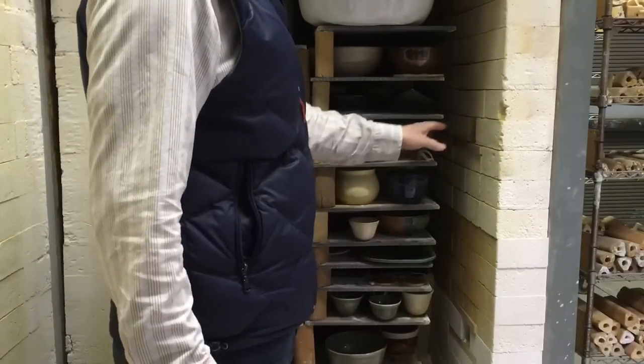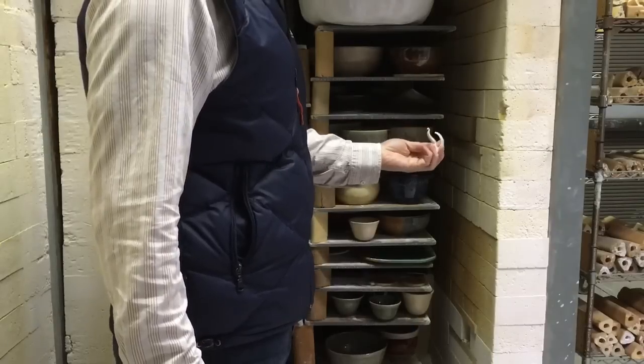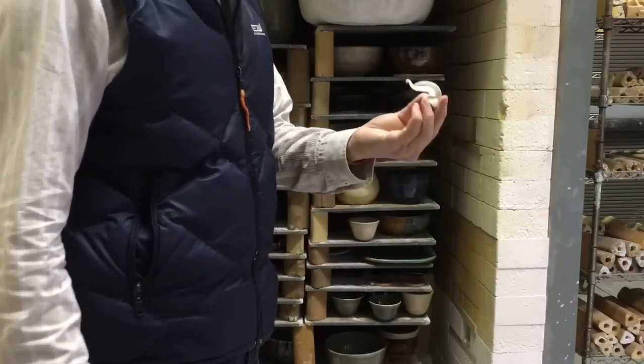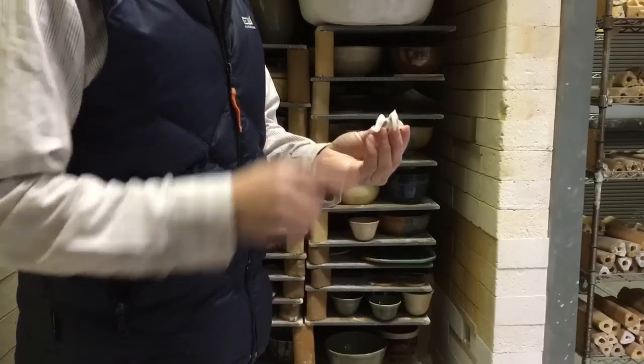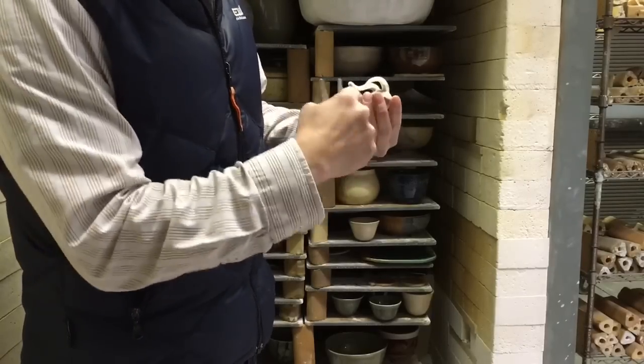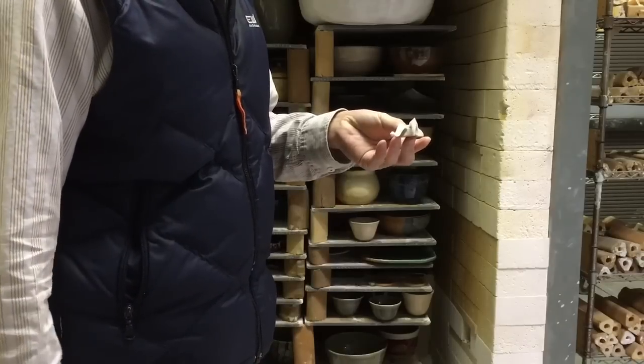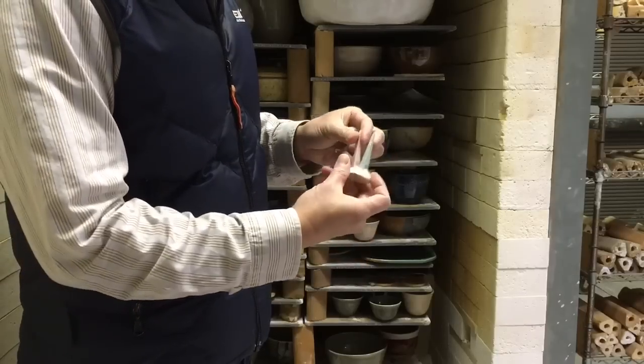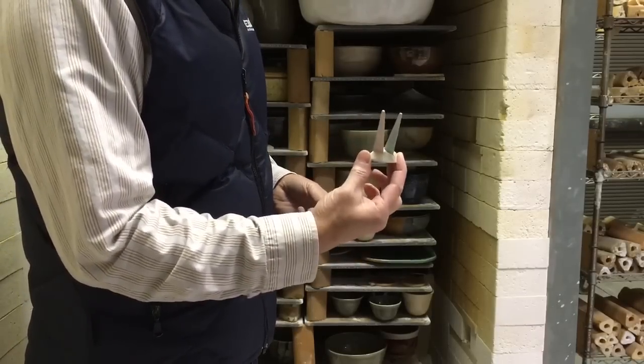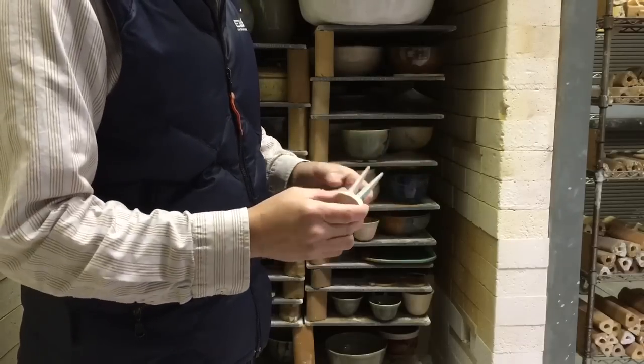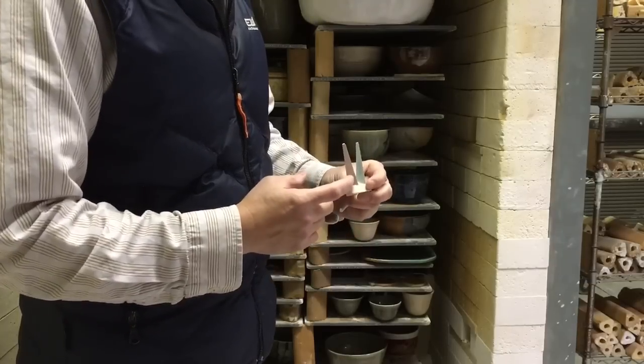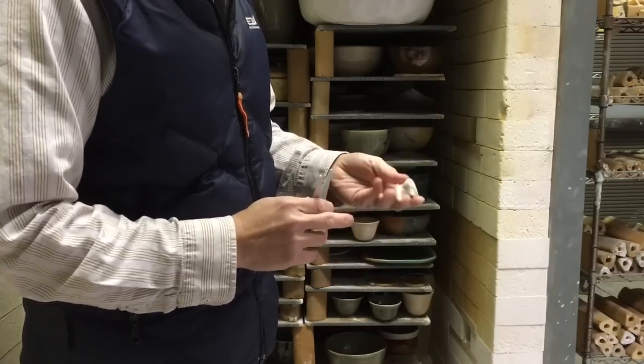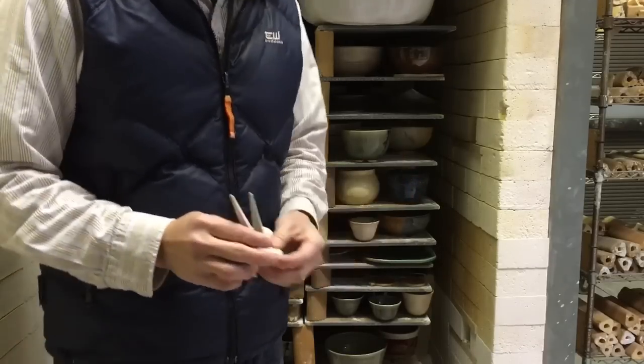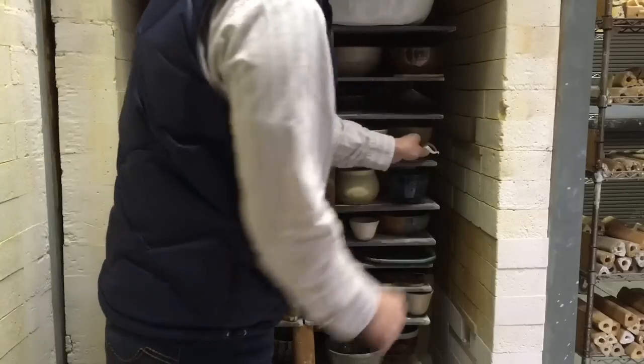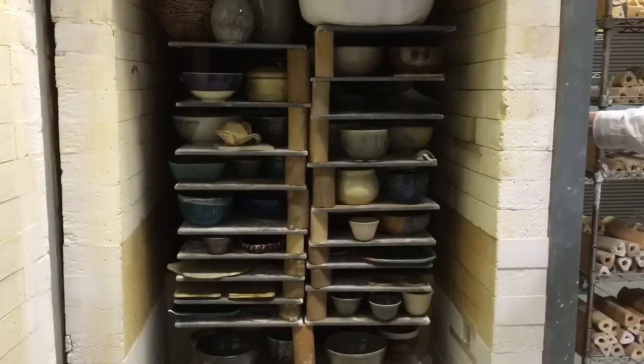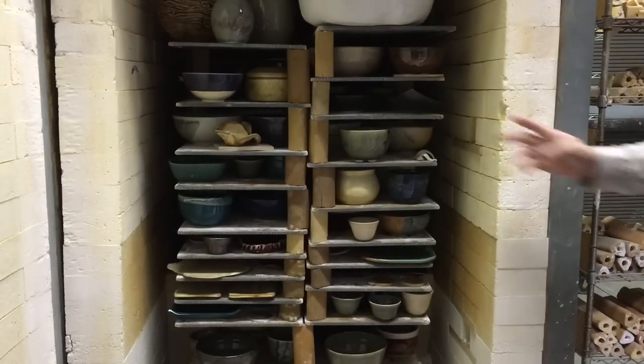Okay, like I told you, we shut down the kiln by telling what cone is on the inside. This is the cone that we fired. It will bend until the tip is kind of touching the level, and we know it's time to shut the kiln off. This is before firing, it looks like this, and after firing it looks like this. You can see there's a number on it: this is cone 10 and this is cone 11. For this kiln, I actually fired to cone 11. Usually it's sitting right here at the spy hole, so you will be able to see it from the outside while the kiln is firing, and decide when to shut the kiln off.